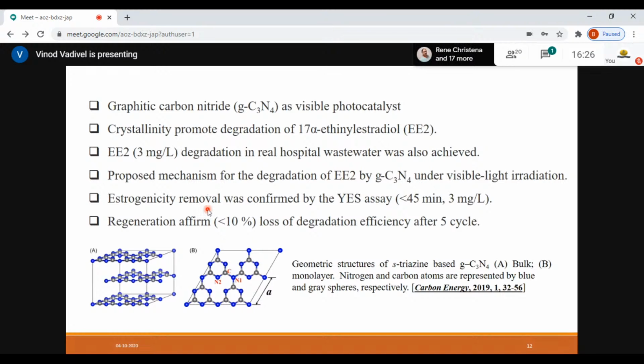And we also studied the estrogenicity removal. So it's not only the chemical part; we also studied the estrogenicity removal using the YES assay, which also confirmed the complete mineralization. And the material was able to regenerate with the same efficiency, with hardly 10% of efficiency lost during the 5 cycles, but probably it was much better.